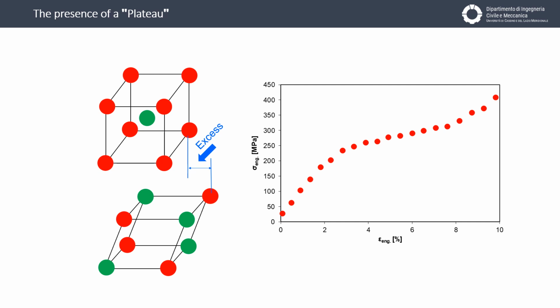The excess of the position of the titanium or nickel atoms is responsible for the decreasing of slope from the first stage to the second stage of the stress-strain curve, because the excess of the deformation when a cubic cell becomes monoclinic relaxes all the cells around this transformation.